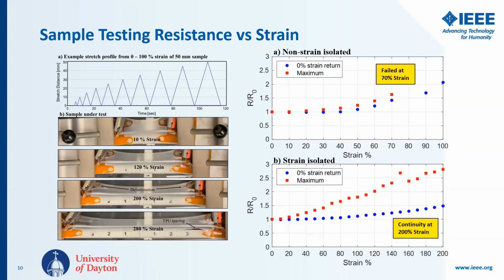So we took a look at our sample strain testing. We took a sample, we placed it into a strain jig, and stretched it progressively higher and higher, and measured the resistance in response to strain. For an unstrain isolated sample, we were able to get up to 70% strain before the sample failed. Whereas with the strain isolated sample, we had continuity up to 200% strain, at which point the sample ripped in half. We did not have a loss of continuity on the strain isolated sample before the sample physically failed.